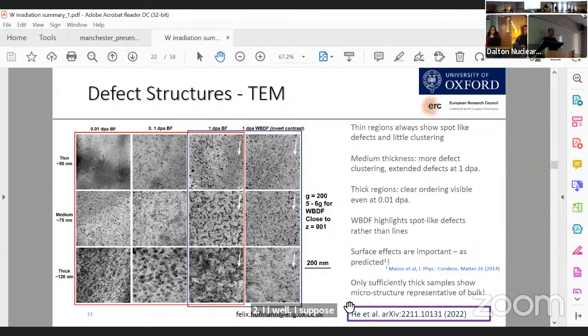Well, I suppose let's look at the positive side. This annealing study that you did shows that we do have a way of getting rid of defects, actually a surprising amount. So I suspect that a lot of these effects become less bad as you go to higher temperatures. And then at higher temperatures, what becomes more important is material chemistry and formation of peculiar phases, segregation, and so on.